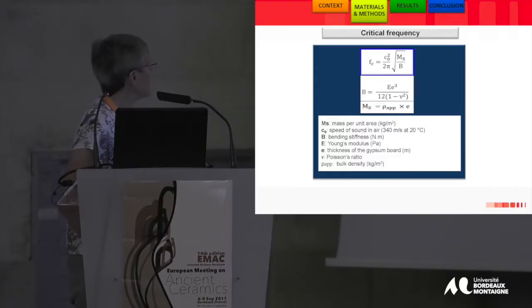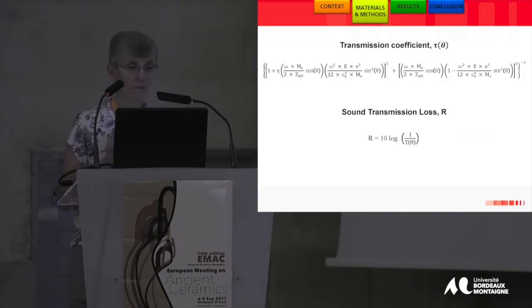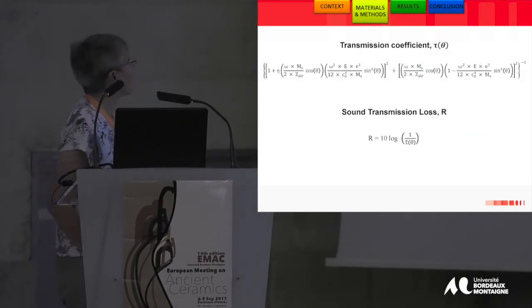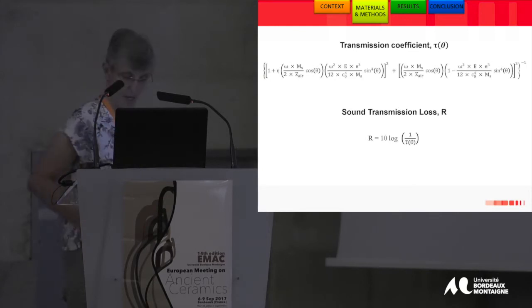So how can we do this? If we look at the critical frequency, there are some material parameters involved: the mass per unit area, the bending stiffness, Young's modulus, the bulk density, and Poisson ratio. The critical frequency is roughly inversely proportional to Young's modulus. For the transmission coefficient, we have a relation which is slightly more complicated, but again we have material parameters, specific mass per unit surface, and Young's modulus.